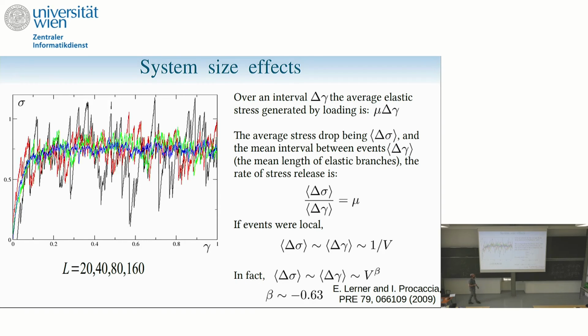Now, imagine that plasticity results from very local rearrangements, totally independent of each other. Then what you expect is that if you increase the volume of the system, the number of events in a unit strain gamma goes like the volume. And each event releases stress in a small neighborhood of fixed size. And so the stress drop, normalized by the volume, should go like 1 over the volume. So if you had local events, the stress release and the interval should decay like 1 over V. That's not what we see, and that's really the trace of avalanche behavior.